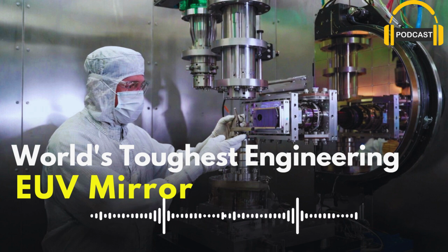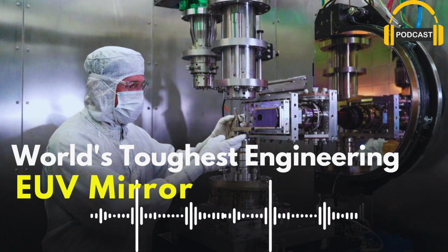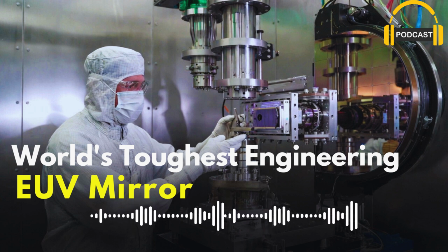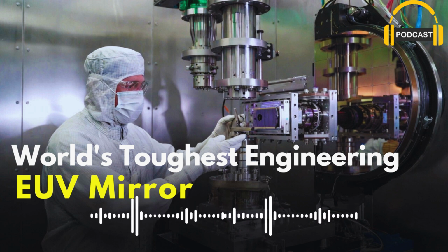But in practice, it was a nightmare. The tin droplets had to be perfectly uniform and perfectly timed, hundreds of thousands per second. The laser had to hit each one dead center with insane precision. The plasma emits EUV in all directions. Only a tiny fraction gets collected by the mirrors. The collector mirrors, also multi-layer, get coated with tin debris and degrade fast. Power output was stuck at a few watts for years, while factories needed 250 plus watts to be economical.